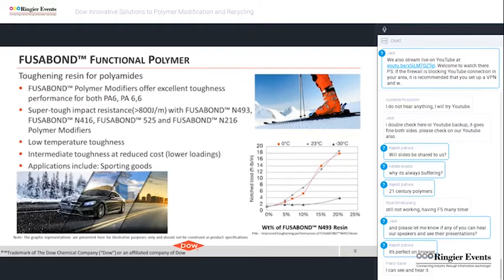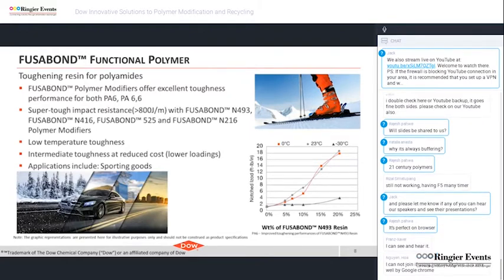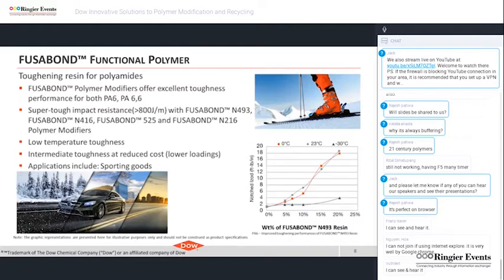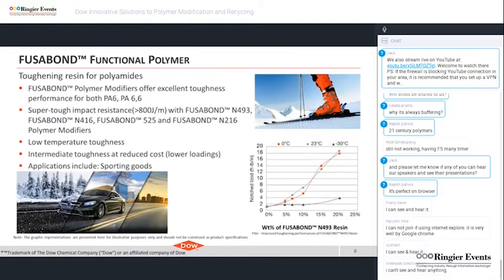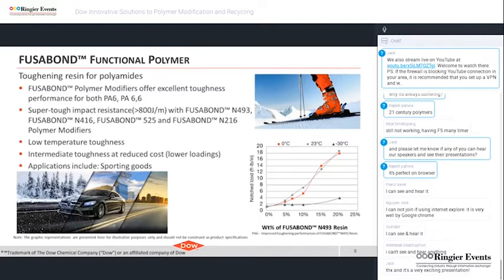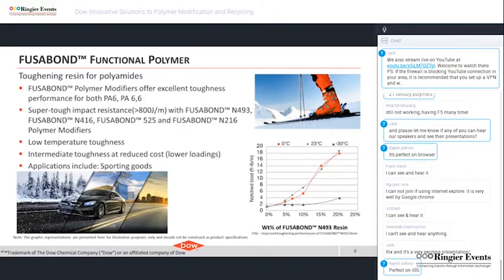We have full range of toughener for polyamides, general to super tough. Room temperature notched Izod will be less than 200 joules per meter for general, 200 to 800 joules per meter for medium, and more than 800 joules per meter for super tough. The chart shows 0 and 23 degrees centigrade toughness increases with increasing level of Fusabond N493 in PA6 compound. Polyamide modification could be done for various applications, including sporting goods.